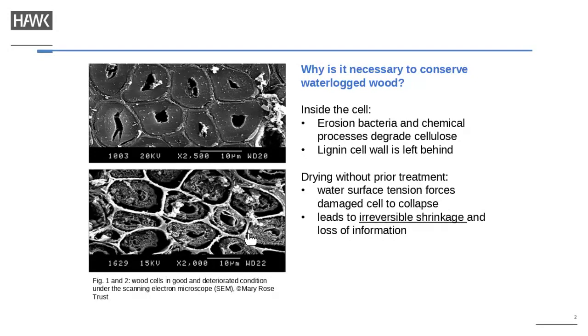So imagine you excavate a piece of wood and the surrounding conditions change dramatically. What would happen if you try to dry it without prior treatment is that the water surface tension would force the damaged cells to collapse, which then would lead to irreversible shrinkage and the loss of the information it might have carried throughout the ages.